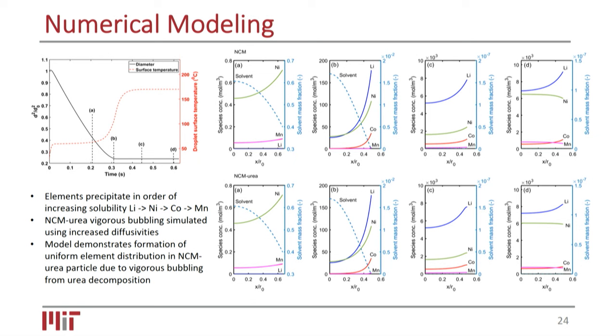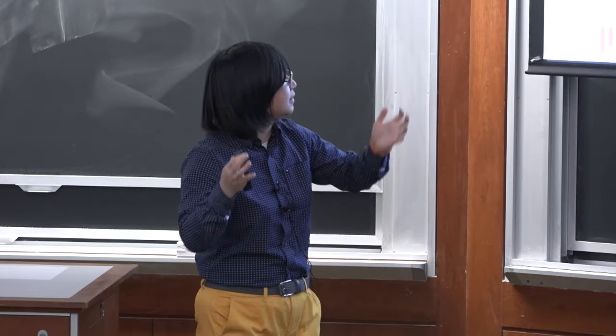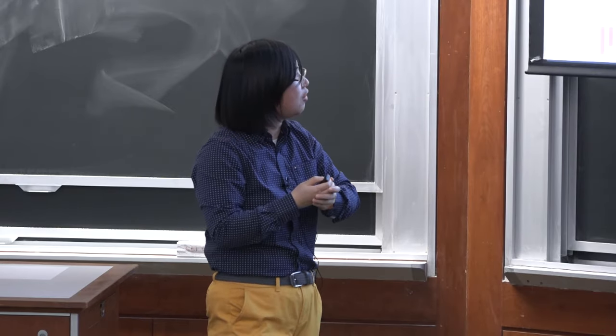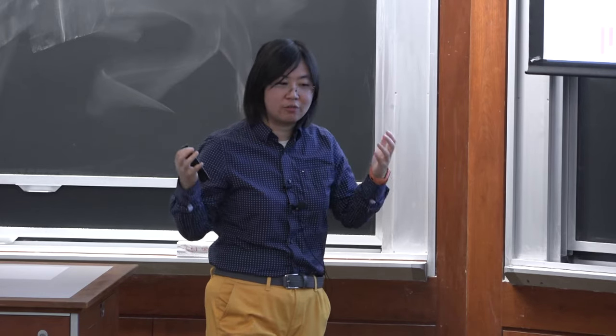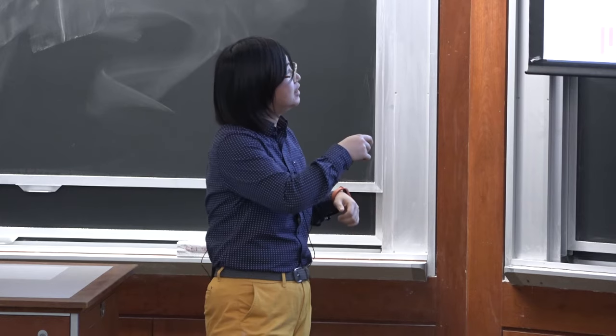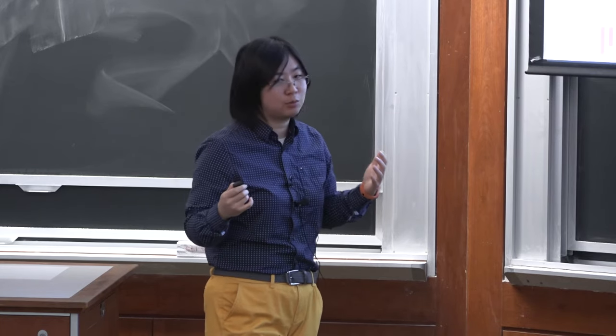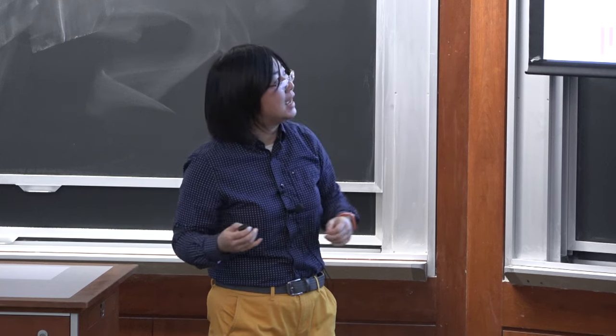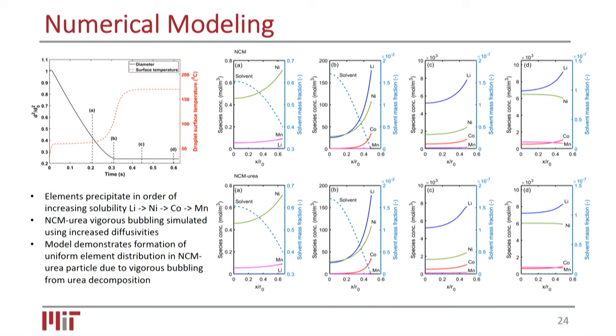And the details cannot be directly obtained from the experiments, so we leverage the computational study to look at what happens. Essentially, without going into the nitty-gritty, as we heat up the particle, the solvent would evaporate, and the concentration of the solute would increase. Depending on the relative solubility as well as its concentration, we start to see that some elements would precipitate from the solution. And the final one would correspond to the actual ratio that we put into the precursor.